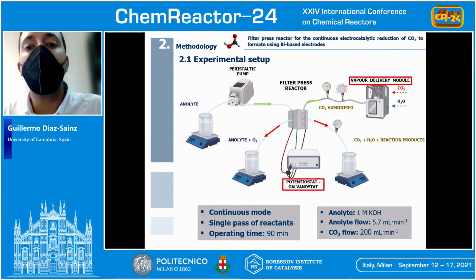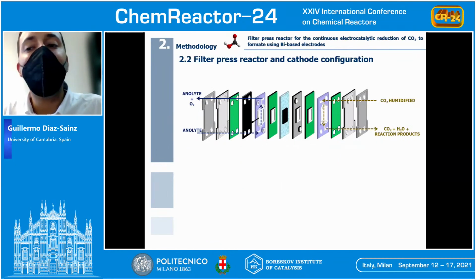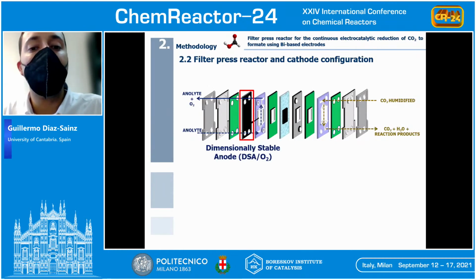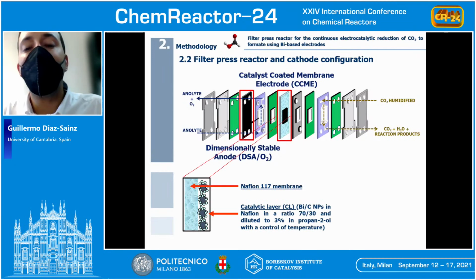We focus on the filter press reactor configuration. The key elements of this configuration are, on the one hand, the dimensionally stable anode, that is a DSA, which favors the production of oxygen, and on the other hand, the catalyst coated membrane electrode, CCM, which acts as an electrocatalytic support, as a separator of both compartments, and at the same time as a solid polymer electrolyte.